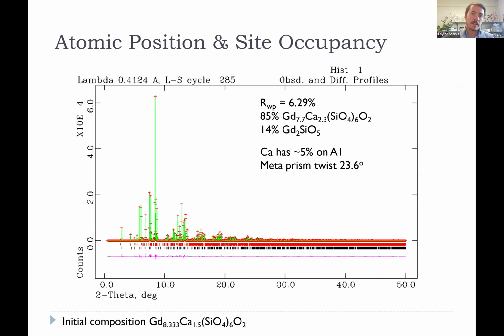So here's what you can expect to see. Here's an example of that same apatite problem where we sent it to a synchrotron to collect it. Take a look now. Our background is effectively 0. It is a very low background. And the intensities, these are 6 times 10 to the 4th. So extremely high intensities, extremely low background. And the sharpness of these peaks, I should have actually zoomed in on it, but they are crazy sharp.